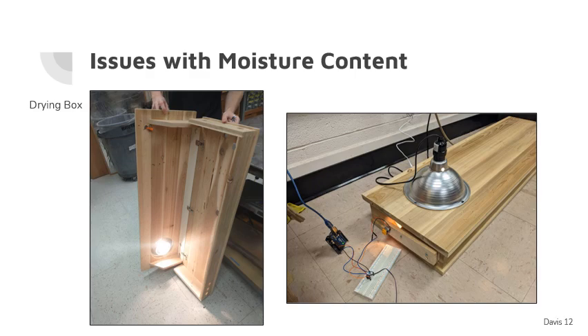We took our raw palm fronds as well as some processed palm fronds and created this drying box for them. It consists of just a wood laminate box that we altered with some air circulation holes at the bottom and the top, a heat lamp that we attached to the bottom to provide warmth to assist in drying, as well as a small Arduino controlled fan at the very bottom that, along with an outlet timer, we had both that fan and the lamp on a cycle that turned them on and turned them off at various points throughout the day to keep some heat and airflow through that box, but not enough to cause any danger of burning the palm fronds or the box itself.